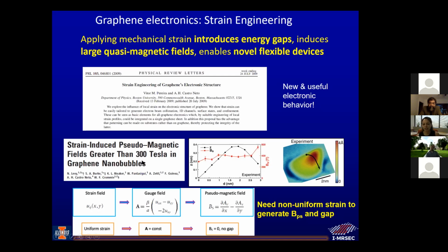to a 300 Tesla field. So this experiment, at least, is complementary to ours, in that it shows that you don't need a perfect bubble, and you don't need a gradient. You just need something that graphene is conforming over a small enough region and locally strained over that region to lead to this effect, and then you'll see it. That's what I took from it at any rate. Does that answer your question somewhat? Yeah, I was just curious because if you're going for a gradient, you'd have a different base structure. Yeah, we're going for something global and uniform.